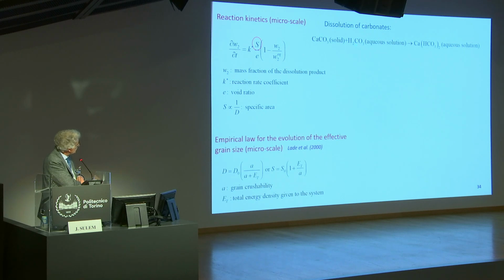So let's take this example, dissolution of carbonates. The reaction kinetics here is written at the scale of the grain, and we have here the dependence of the kinetics. W2 is the mass fraction of the dissolution product. It's one other kinetics equation. It depends upon the specific area of the grain, which can be written as proportional to the inverse of the grain size. Here we've used an empirical law for the evolution of the grain size at a micro scale, inspired by the work of Paul Lade.